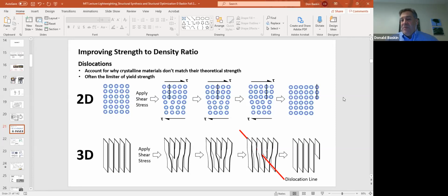So you have a continuous lattice that might go on for several centimeters or inches, all of the same orientation, or very close to the same orientation. But yes, you still end up with dislocations in that case too. Fewer, far fewer, and that's why single crystals can be brittle, like silicon wafers are very brittle. There are a lot fewer, but there still are dislocations in those materials.